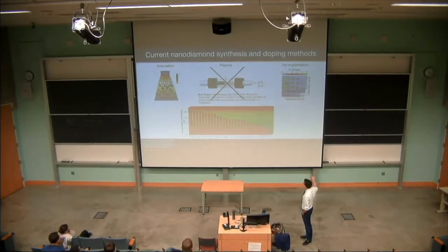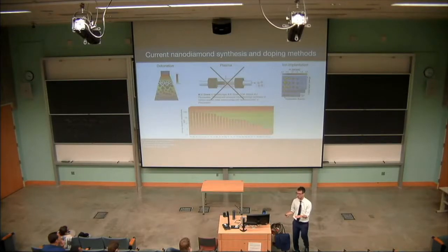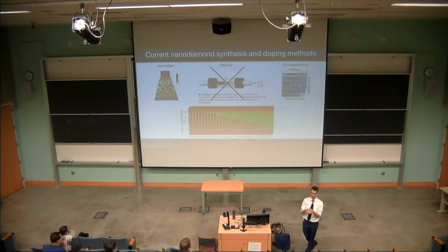Last, and perhaps the most successful way of making doped diamond is actually with ion implantation. This is a mechanism where you can take a substrate of diamond and you can literally launch an ion at it. This will break through the carbon lattice and implant in the diamond. And this is somewhat deterministic. But you can imagine that you now break up the diamond lattice. And again, there's still this trouble where you're not going to localize more than one element onto a single lattice site.